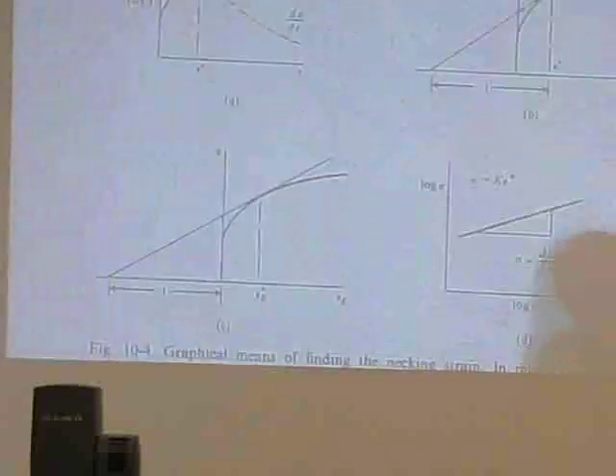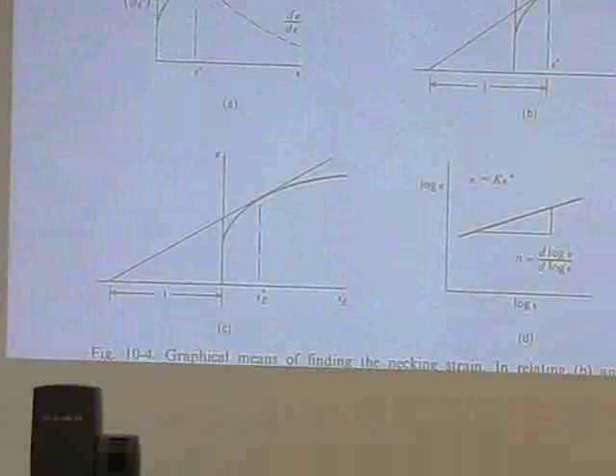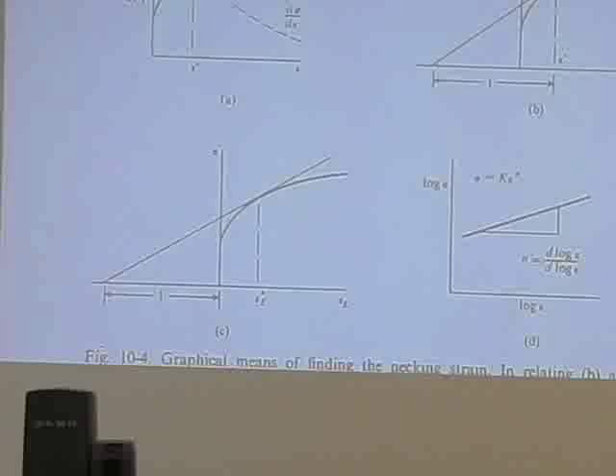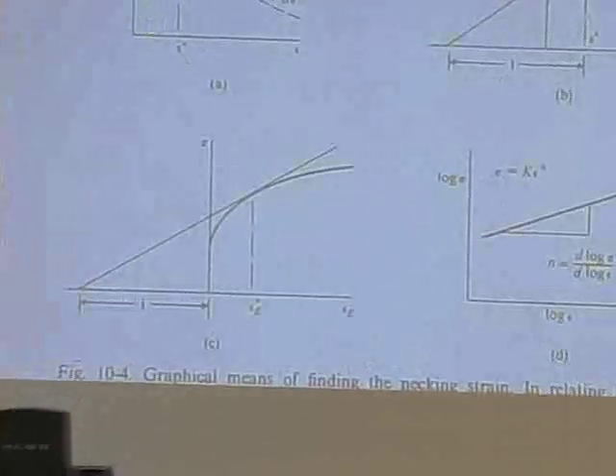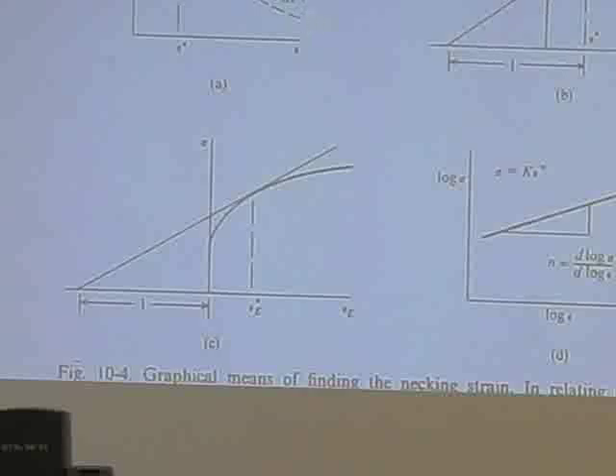Well, what does that mean? Well, geometrically, if you want to try to figure it out from a graph, you can plot stress versus strain, this is the stress strain curve. You can also plot d sigma d epsilon, which is the slope of this, there's the slope of it, d sigma d epsilon is this dashed line coming down, and when those two are equal, that is your necking strain, epsilon star, okay?